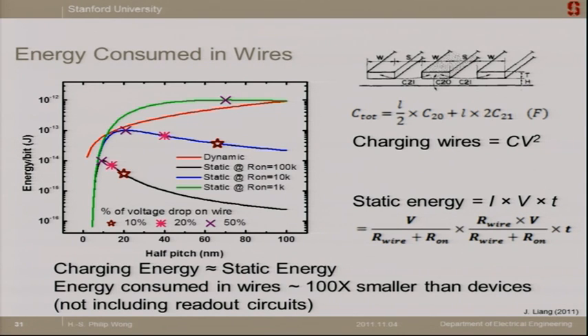So here is the dynamic energy. This is CV squared charging energy. This is of the order of 1/10 of a picojoule or so. And the green, blue and black curves are the energy consumed in the wire for various cases of the on resistance of the memory cell itself.